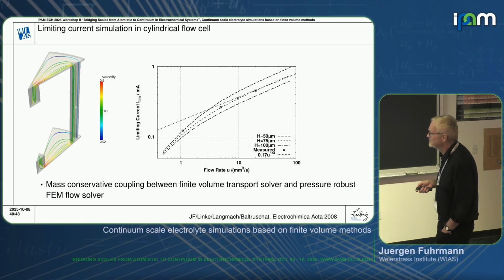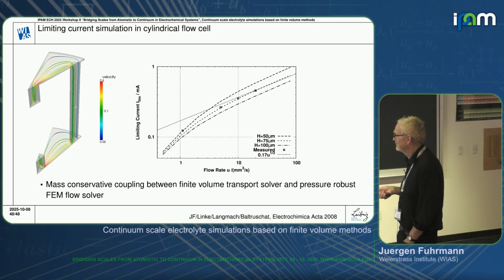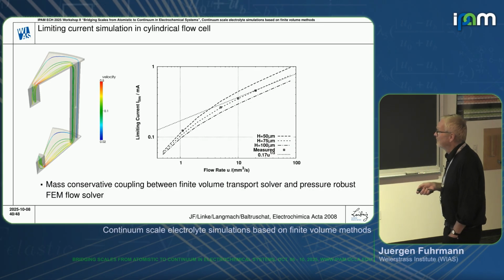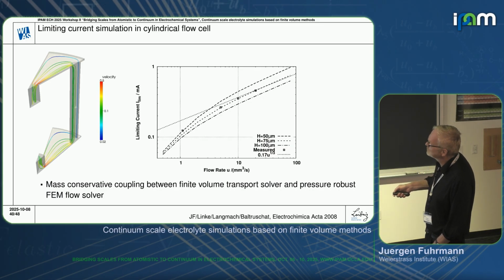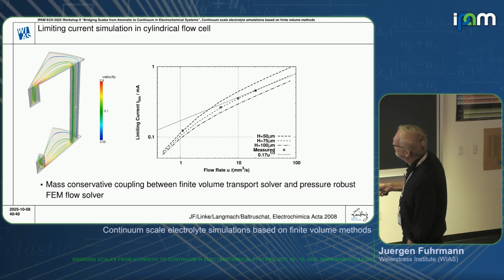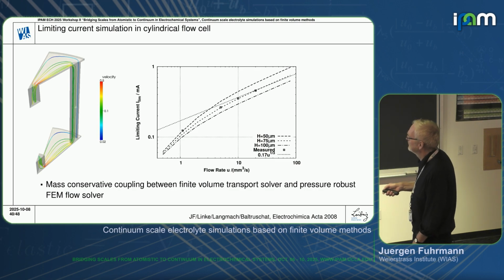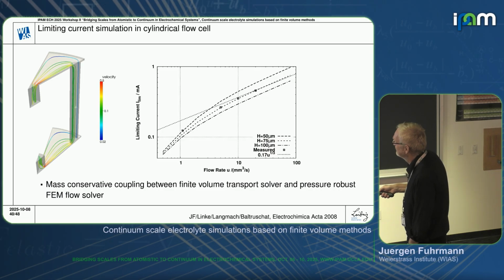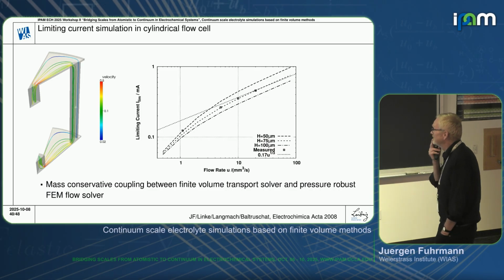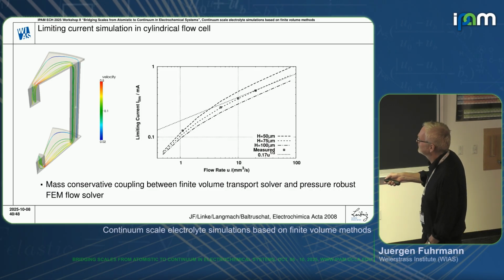And then with the simulation approach, we can also work on different flow cell geometries. We had some cooperation with Helmut, with the Baltruschat group in Bonn, where we did Navier-Stokes solutions for their flow cell, also then coupled to species transport, and then we can see that we don't have this kind of really third root dependency on the flow rate for their flow cell, but we can still take a look at the limiting current and compare it, and then for instance match this to the cell height, which was a little bit unclear by the construction of the cell.